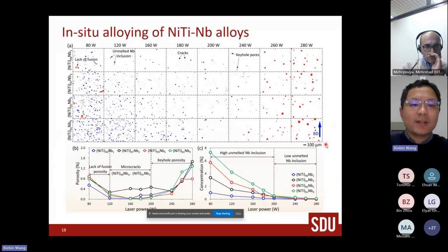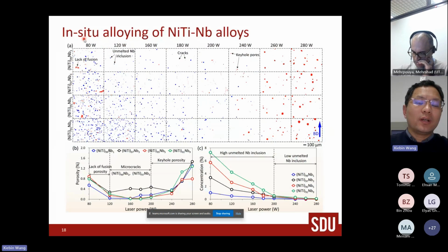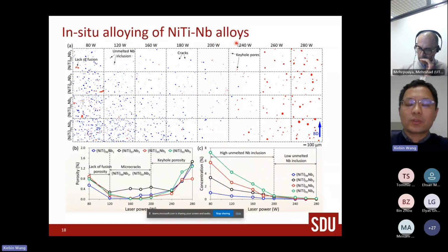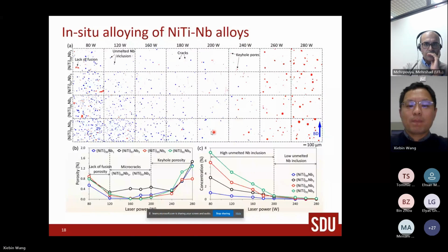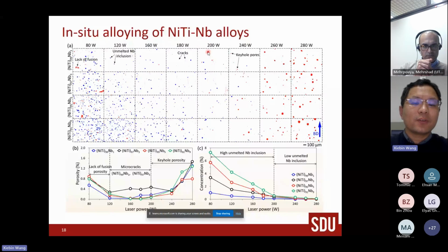And then we did the process optimization. This time we changed the laser power, and at low energy input, there are a lot of unmelted niobium particles. The blue dots are niobium particles. And at higher energy input, there are a lot of keyhole pores. So for the samples printed with 200 watts and 240 watts, there are fewer keyhole pores and fewer unmelted particles. So we selected 200 watts to print all the nickel titanium niobium samples. And of course, as expected, for the samples with 1% and 3% niobium, there are solidification cracks, these red lines. Here are cracks.